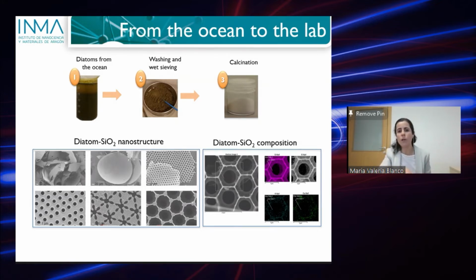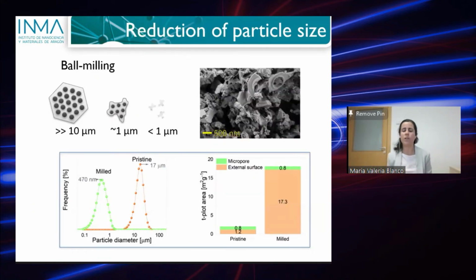So what we try to do is to adapt some experimental procedures to use this material on an anode. The first thing we wanted to do is to reduce the particle size of the diatoms. For this, we implemented some ball milling procedures that are not quite easy because the silica shells of these algae are quite hard. At the beginning, the algae were really damaging the balls because they were harder than steel. So we had to adapt a bit and use some balls made of tungsten carbide, and then we successfully ball milled the algae. We moved in particle size from an average size of 17 microns to about 470 nanometer